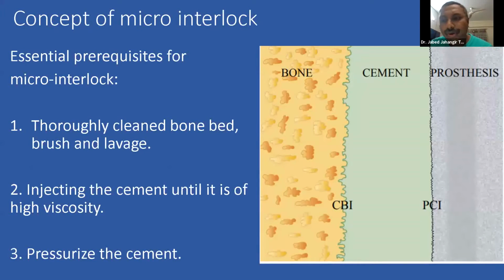One important concept is micro interlock. You know, in the femoral canal and in the acetabulum, there is a trabecular bone which has some interdigitation of the bone or trabeculae, in which cement penetrates, and about 300 kilopascal cement penetration pressure is needed to overcome the femoral canal blood pressure, which tries to displace cement from interdigitating within the trabeculae. So what we need: thorough, clean bone bed, brush, lavage, injecting cement while it is maintaining its viscosity so that it overcomes the pressure within the femoral canal that tries to displace cement bonding within the bone, and pressurization of the cement.